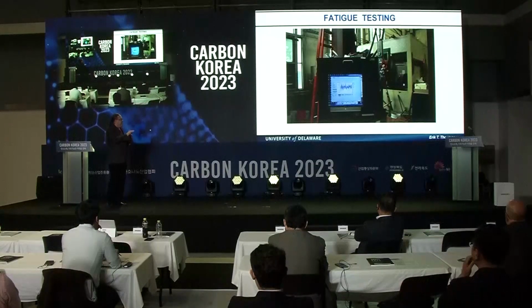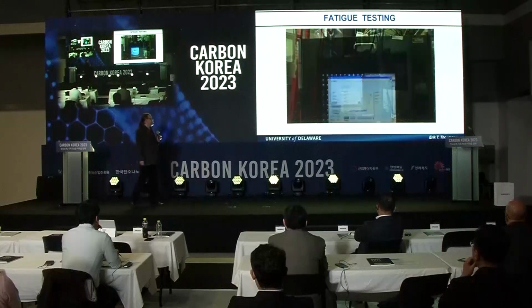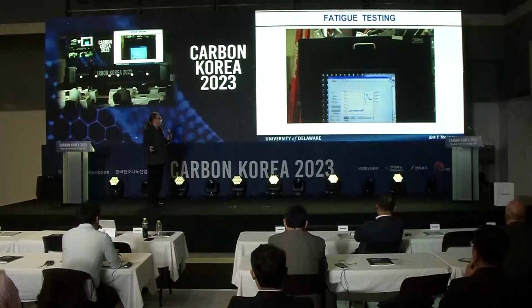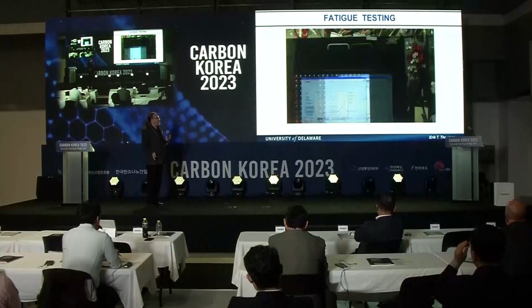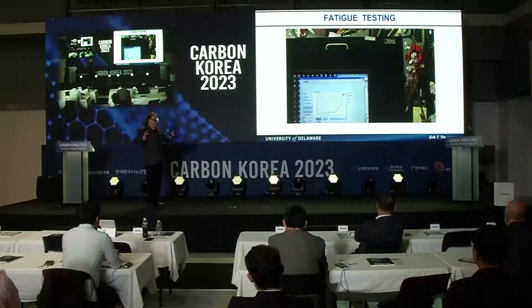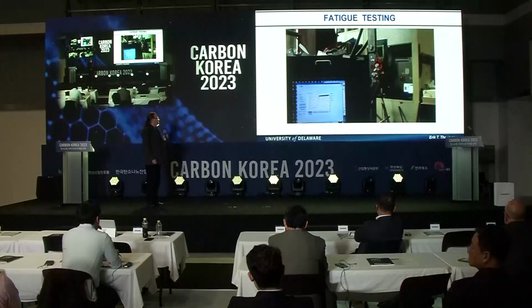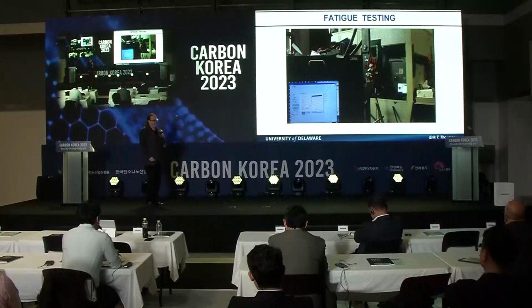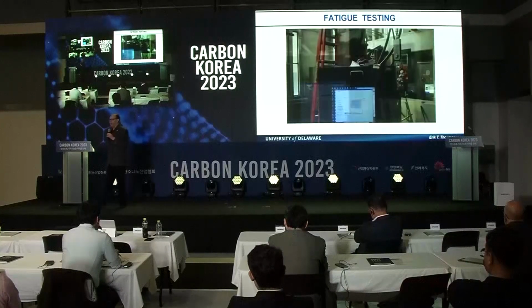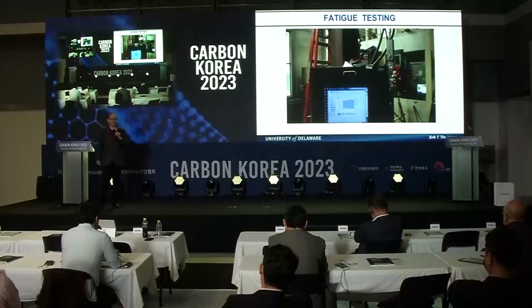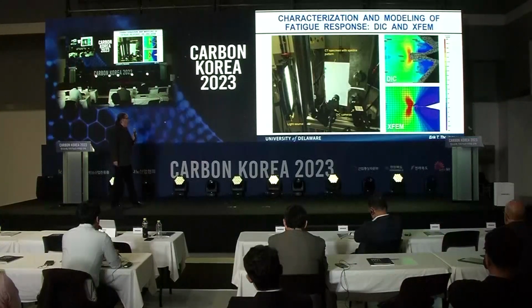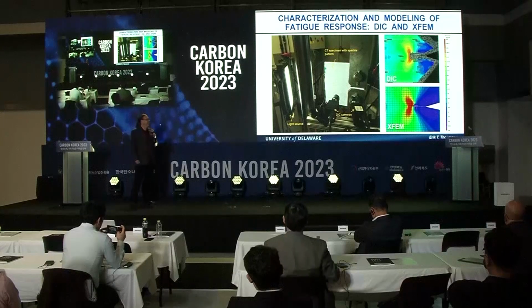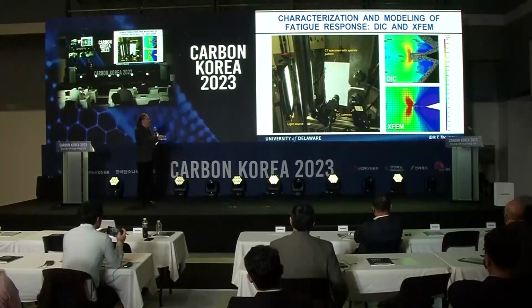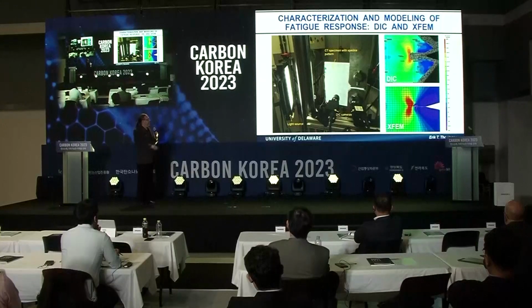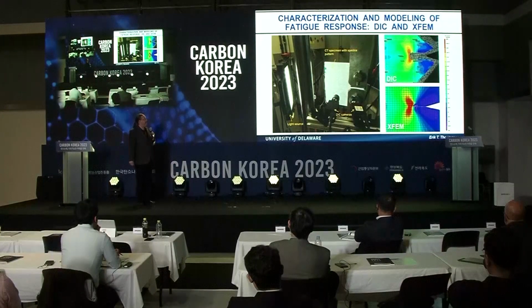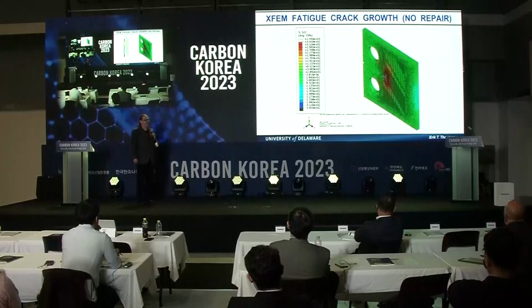So this is actually the specimen that you saw in the previous picture, where the sensor is on a compact tension specimen. Although it's not very compact, it's quite large. And what you can see on the response is the sensor response so that we can detect the load. But most importantly, we can detect the crack extension. And so we've done that in the lab. We've done both modeling, what you see on the bottom is some finite element modeling, as well as digital image correlation to track the motion of that crack. We also have a sensor on the other side.